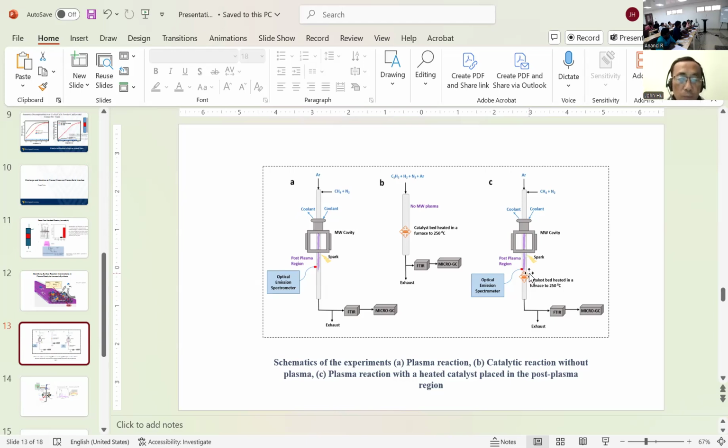So the challenge is you have to make sure you are doing plasma catalysis, not just conventional catalysis. The reason is that when the plasma reaches the end of the zone, the species try to find an electron or something and disappear. That means they could capture some other molecule and disappear. So your job is to put the optical emission spectra on the surface and make sure the incoming species is plasma. Then you are talking about plasma chemistry. Follow me? Otherwise, you are talking about conventional.